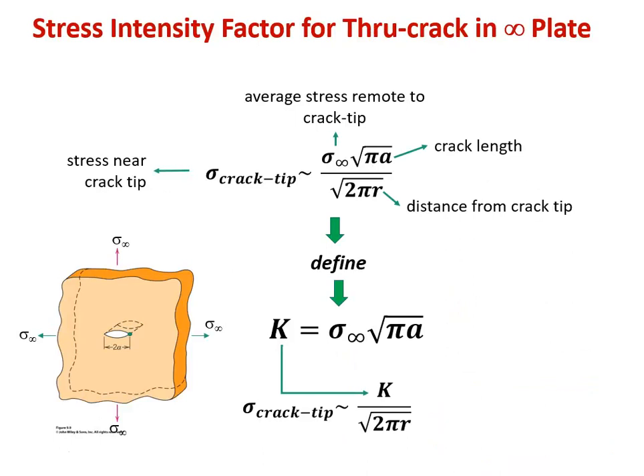So let's look a little harder at our semi-infinite plate with our elliptical crack. We have basically the same figure over in the lower left-hand corner of this slide. This is our same plate. It's got some thickness. It's infinitely large in two directions, and we're yanking on it with sigma infinity in two directions at once. So here's our biaxially loaded plate. We can define what's called a stress intensity factor for a through crack in this semi-infinite plate. So this is just for this particular loading scenario, through crack of total length 2a.